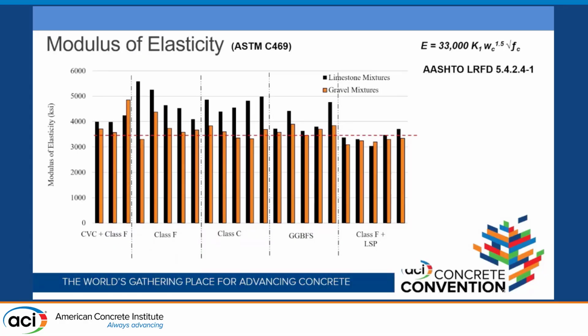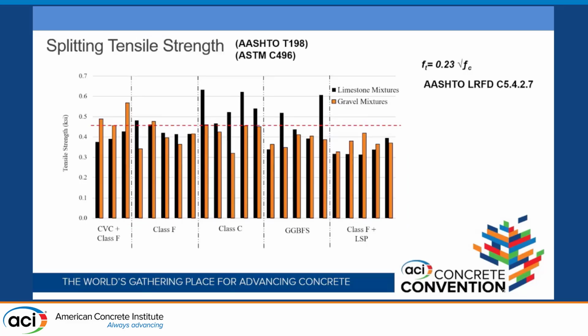Looking at the modulus of elasticity for all these mixes, again, they're almost the same range. Modulus of elasticity originally had a plus or minus 20% by default. And we get slightly less, of course, with the ones with 35% replacement. And that's consistent with the lower compressive strength.